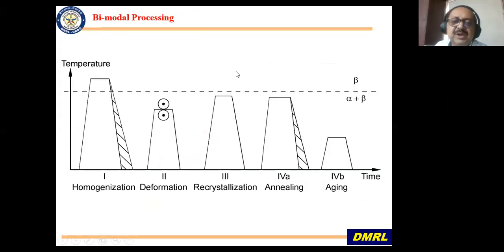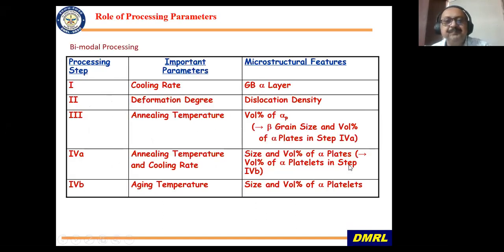Then you can also do a bimodal processing, as in case of Ti-10V-2Fe-3Al. Wherever you have fatigue kind of application, finer structure is much better, and that is done for metastable beta alloys. And similarly, just like alpha plus beta alloys, they are alpha plus beta deform, and then most of the time these two treatments are combined together, recrystallization or solution treatment, and then finally aging.